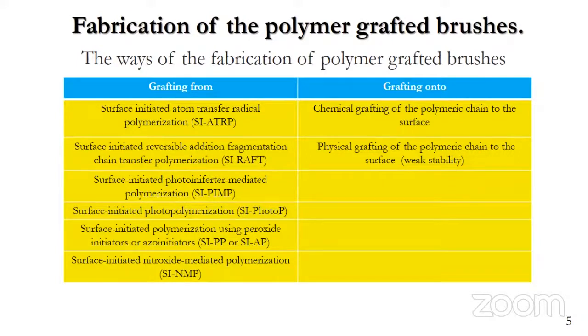In turn, in the grafting from technique, the polymer chain is grown from the pre-modified surface in a two-step procedure, including grafting multifunctional surface modifiers to the solid surface, followed by fabrication of the grafted polymer brushes coating using surface-initiated radical polymerization. Also, this method allows a better control of some properties, such as grafting density. It remains difficult to establish in large surface areas and unprotected atmosphere, and this method, we use this approach in our work.